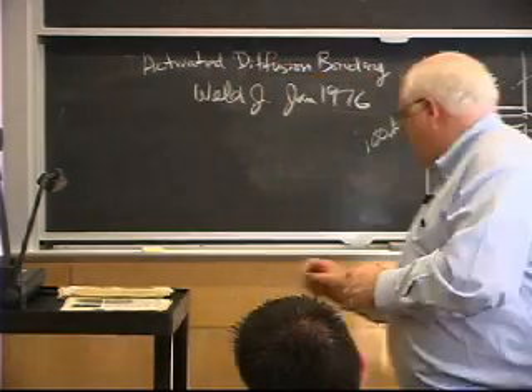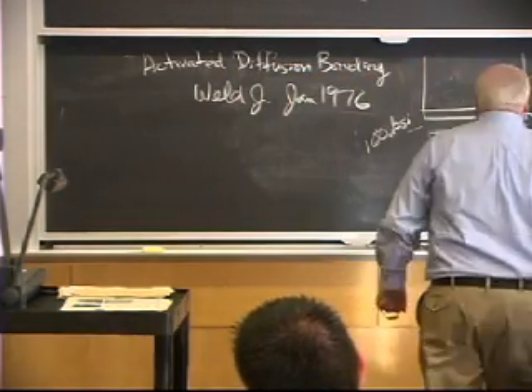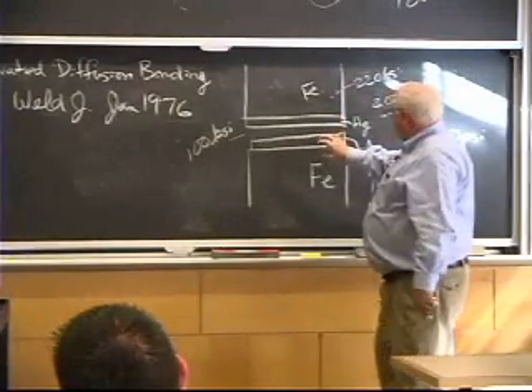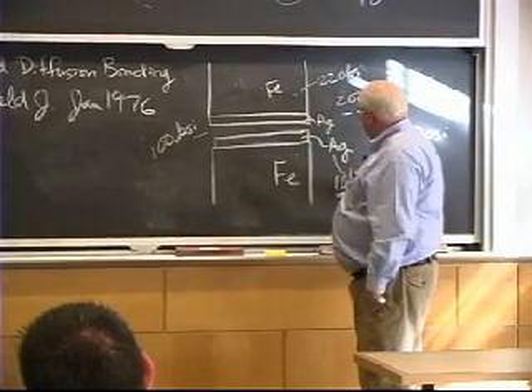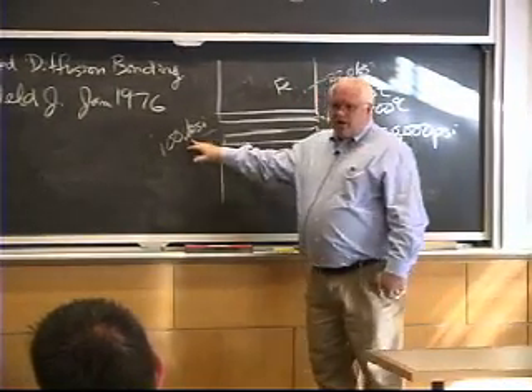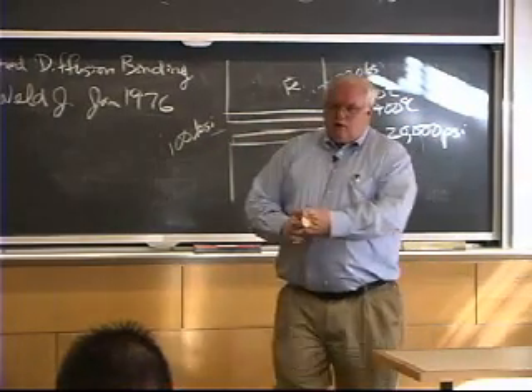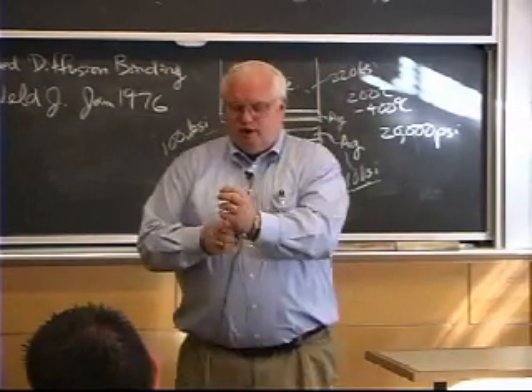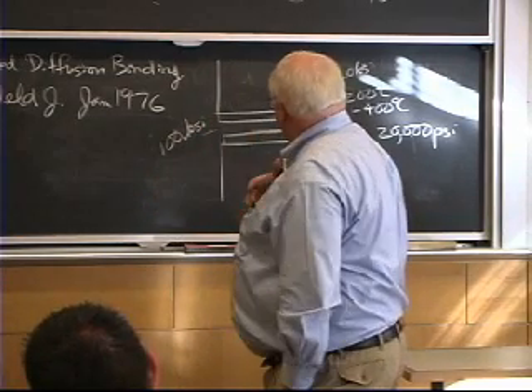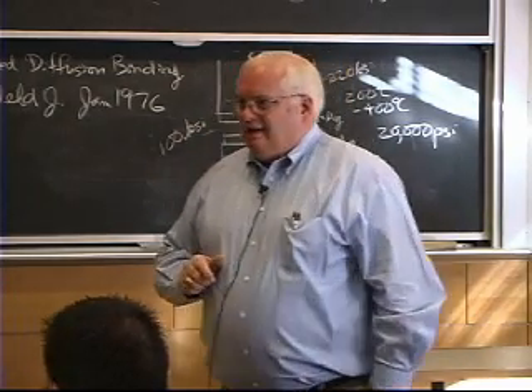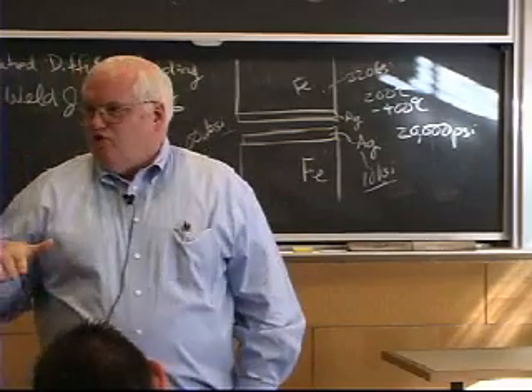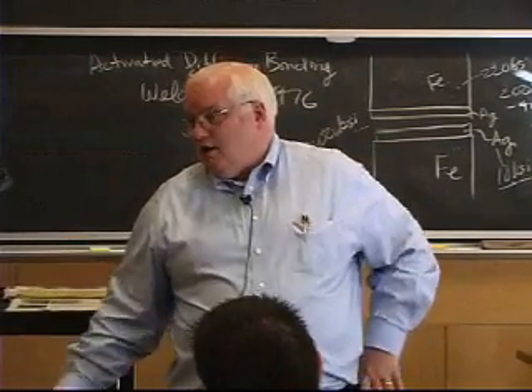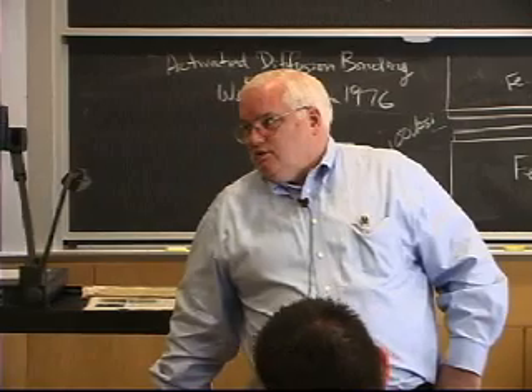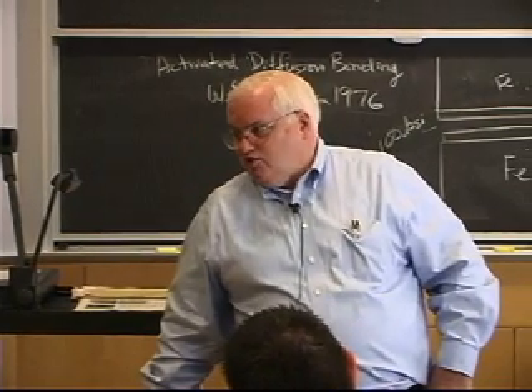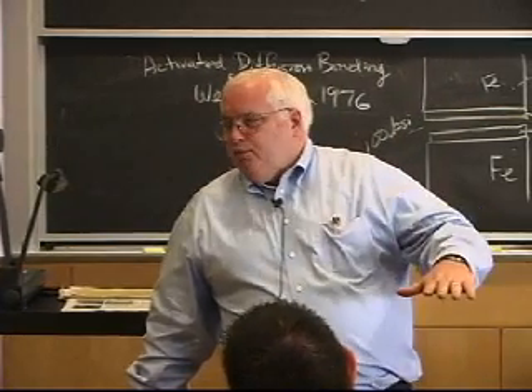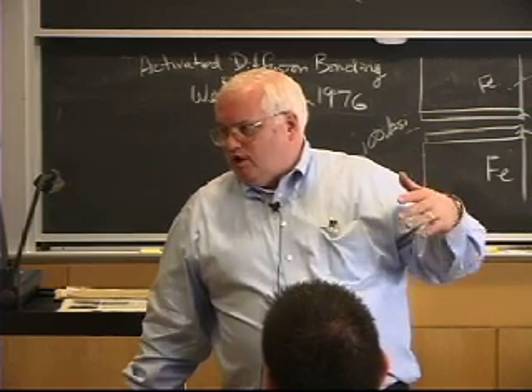But activated diffusion bonding, here's an example of squeezing this together, having very thin silver layers, and you can say, well, if I've got a silver layer that only has 10 ksi strength, how do I get 100 ksi in the joint? Well, that's contact strengthening, and we're going to get to that when we do the brazing stuff. But the point is, they made a diffusion bond and bonded 2 pieces of iron together using silver, and the silver melts at 960 degrees centigrade, and the iron melts at 1500 degrees centigrade, but they actually made the joint at 400 degrees centigrade, below this 0.6 of the absolute melting point that I told you about.